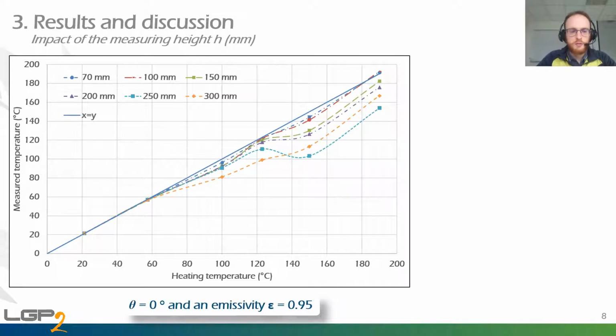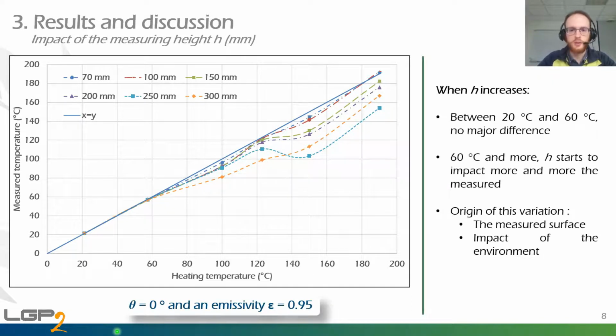So first of all, let's talk about the impact of the measuring height h. Here you have the measured temperatures versus the heating temperatures for different h. Here, theta and emissivity epsilon are fixed. As you can see, when h increases, between 20 and 60 Celsius degrees, there is no major difference. However, for temperatures above 60 Celsius degrees, h starts to impact more and more the measured temperature.